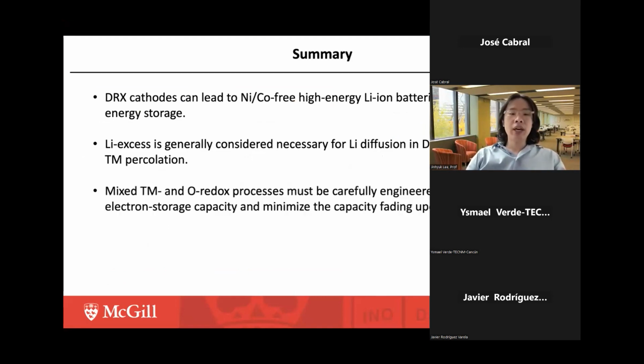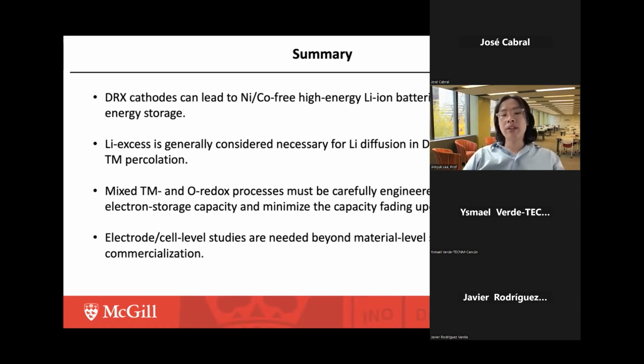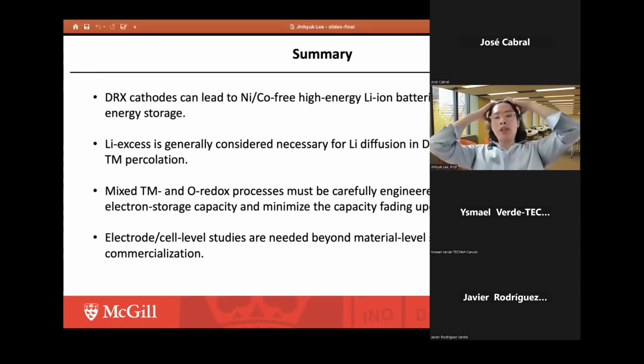And I wanted to show that because of the lithium excess composition, we need to rely on the mixed transition metal and oxygen redox process, but this needs to be carefully engineered to achieve a high capacity with minimum capacity fading. And finally, I would like to show that the electrode and cell level studies are critical beyond the material level study for the DRX materials, for the practical installation in lithium-ion batteries.